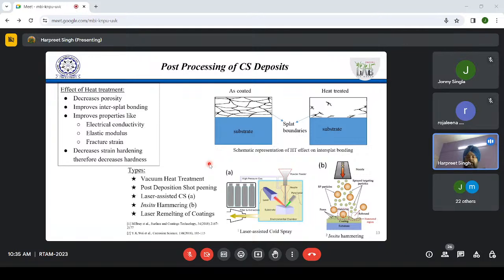As I told you, if there are some challenges in terms of getting the desired properties, people have done some interesting work in terms of post processing of these deposits also. One approach would be heat treatment, right? We all know that it can mitigate the porosity, and it can improve the intersplat bonding, just like in your sintering. For example, this is an as-coated substrate, right? So this is the coating. In the coating, you will see very clearly the splat boundaries. But once you heat treat, these splat boundaries can be merged and you can get better intersplat bonding, right?